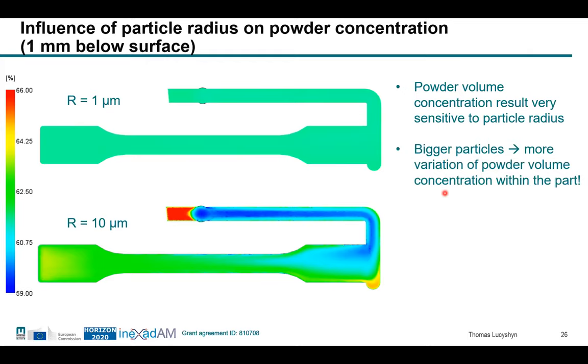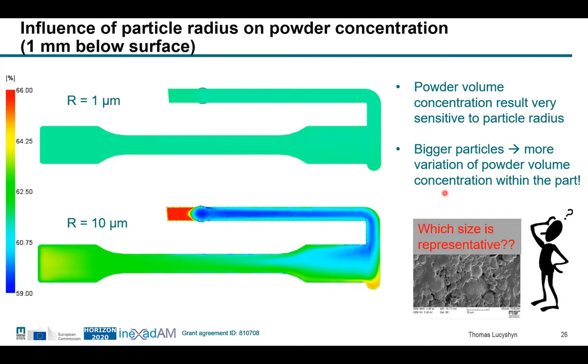And in general, bigger particles have shown more variation of the powder volume in the part, which brings us back to this initial question: which size is representative if we have a distribution in reality and can only enter one value?